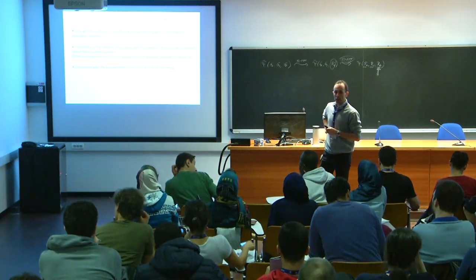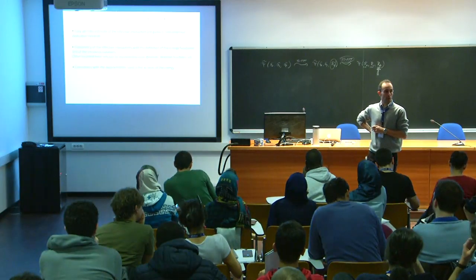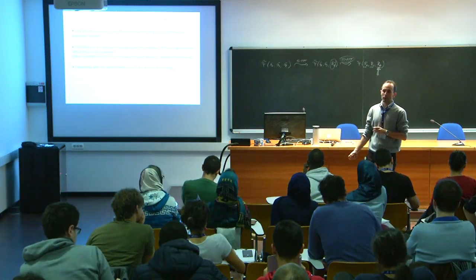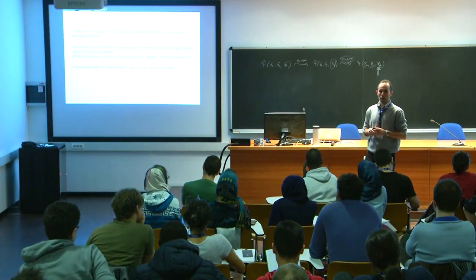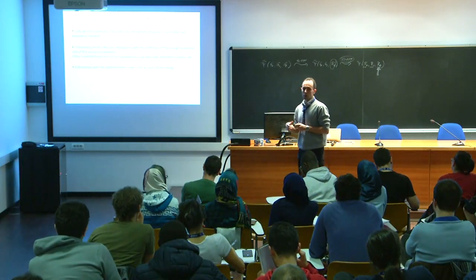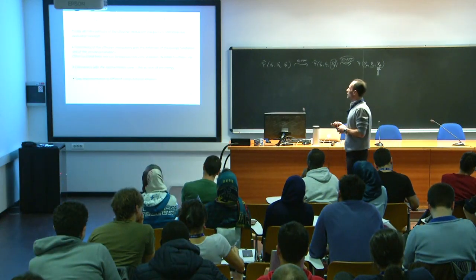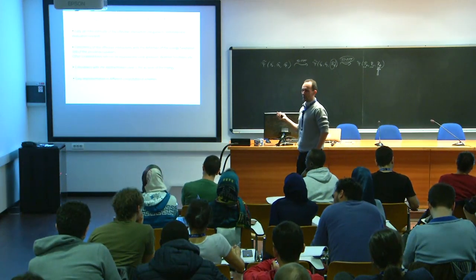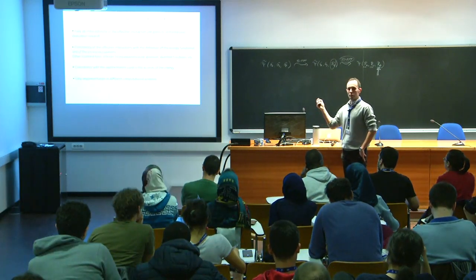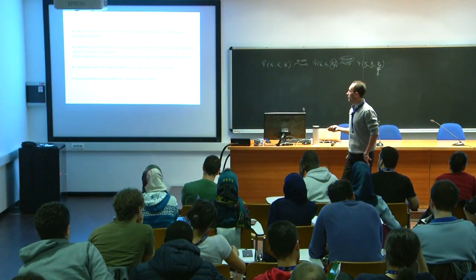Okay, and remember that the plus U thing is a correction. So you should be consistent with the approximate functional you aim to correct. So if you want to correct an LDA functional, compute U for the LDA functional, and expect to get a different value if you want to correct instead a GGA ground state. Okay. And once you have implemented the DFT+U, implementing this way of computing the effective interaction is very simple. I mean, it's just a piece of the functional that you already have.